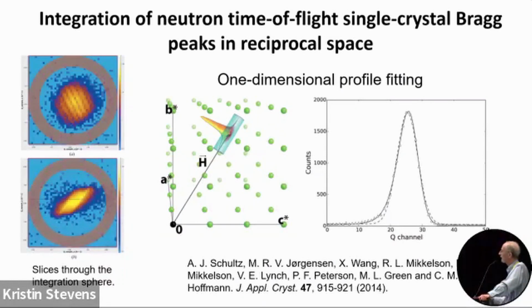And so what we've done here is fit this cylinder here, center it on the peak, and align the cylinder axis with the HKL vector. And then all the neutron events are added to the profile along the axis here to give a peak that might look like this, the solid line. And then we can fit that to a Gaussian convoluted with an exponential term. And so here's just the Gaussian, doesn't give a good fit here, but then with the exponential fall off, we'll get really nice fits. And then using the calculated integrated intensity under the peak actually gives better results than peak minus background integration, either one-dimensional or three-dimensional, whatever. So in certain cases, this actually gives the best results.